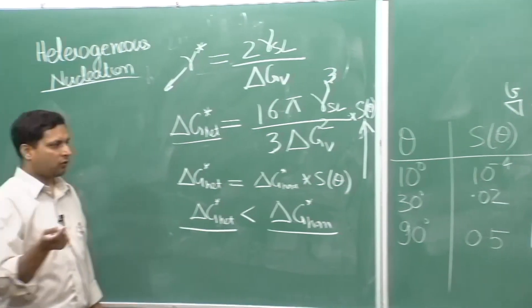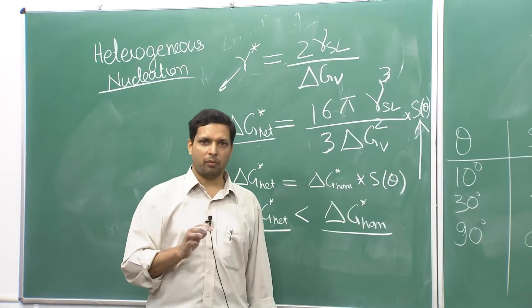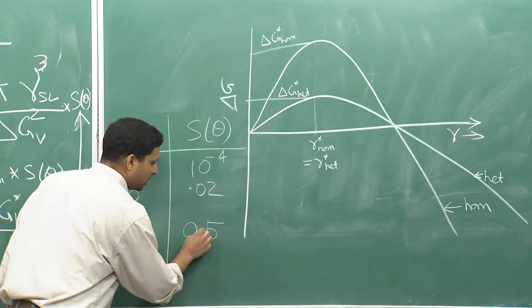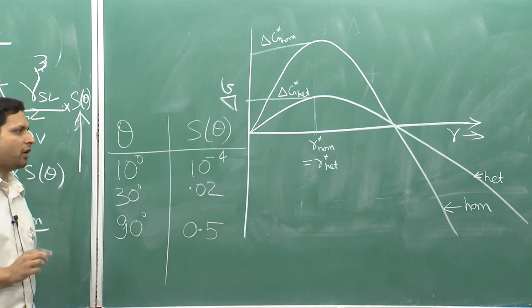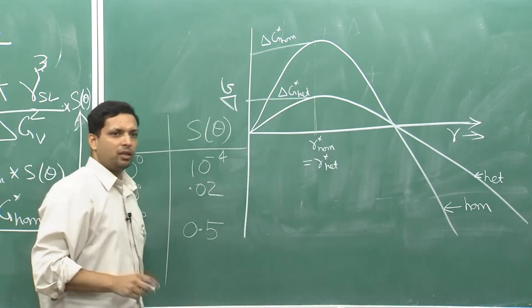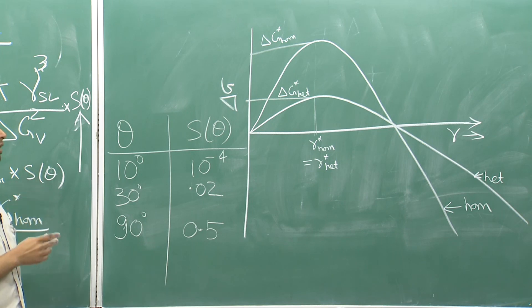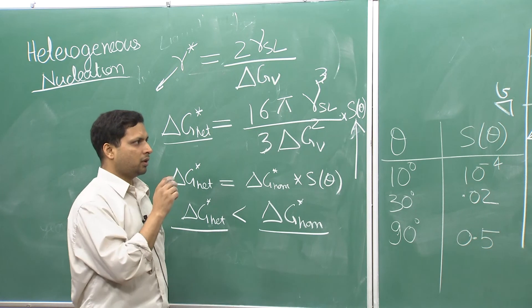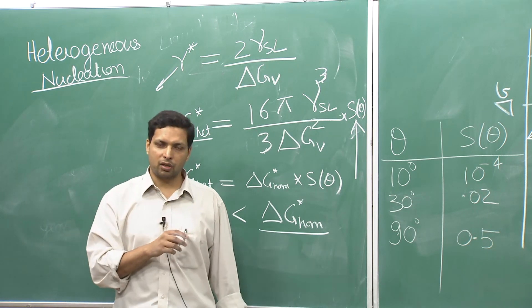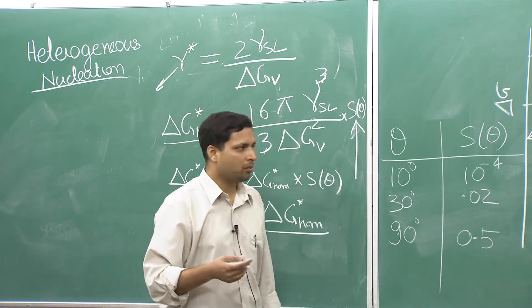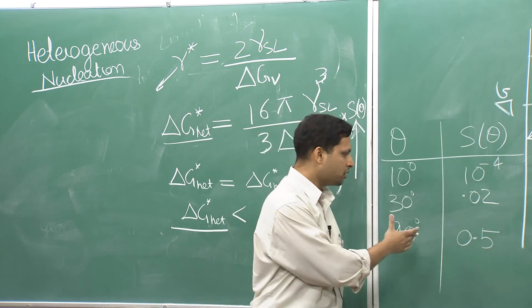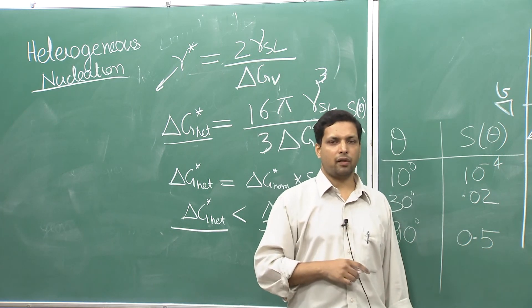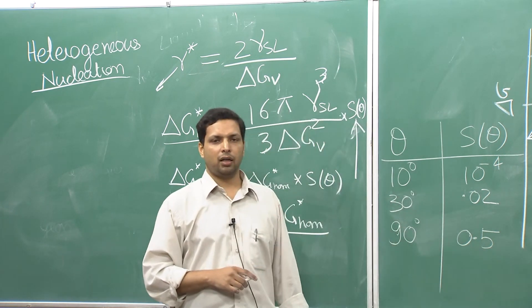Even for very large θ values, since S(θ) involves cos θ, going beyond 90 degrees makes no further difference. At θ = 90 degrees — the maximum effective case — S(θ) = 0.5, so ΔG*_heterogeneous is still half of ΔG*_homogeneous. Since this ΔG* term appears inside the exponential in the nucleation rate equation, even this factor of 0.5 leads to a very large difference in nucleation rate — which we will look at in the next class.